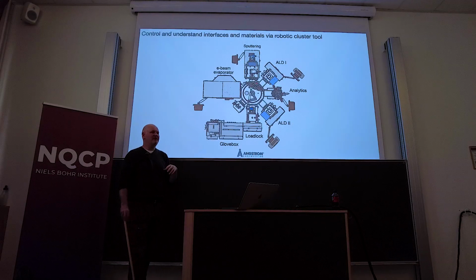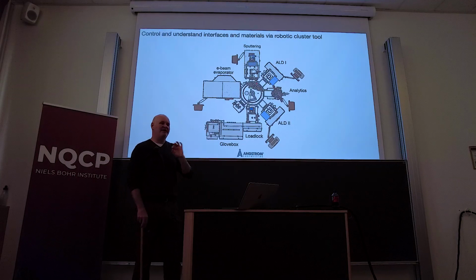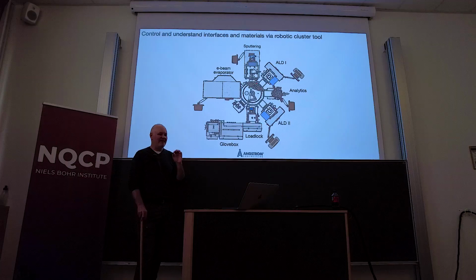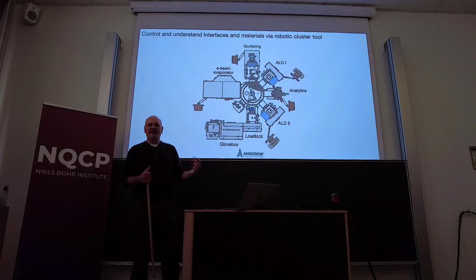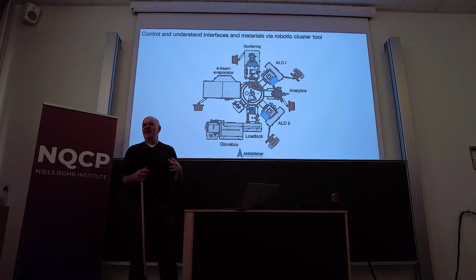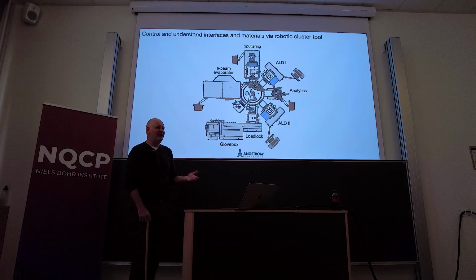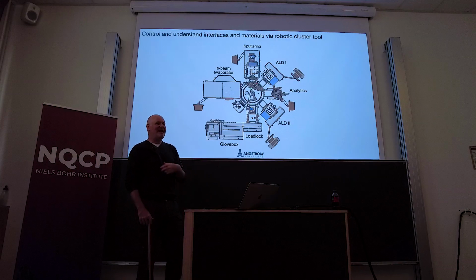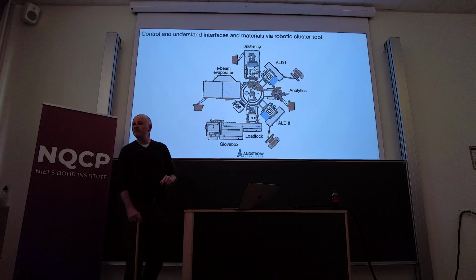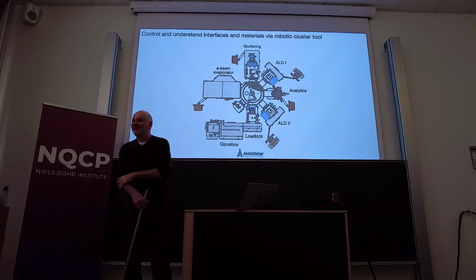For those of you who don't know, atomic layer deposition essentially allows you to grow materials sub-atomic layer at a time. So angstrom level precision over growth. It doesn't have the same degree of control as something like MBE because this is all done at low temperature, so you're not doing epitaxy or anything like that. It is most commonly used for passivation layers and for dielectrics. So in semiconductor industry, it is heavily used, but mostly for dielectric spacers. What do you mean by less than atomic layer? So it is less than atomic layer.